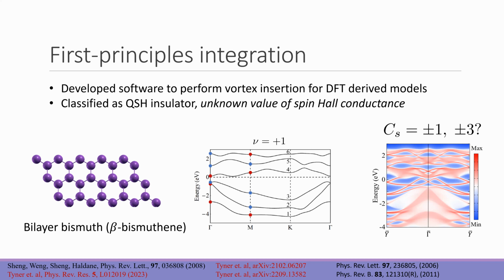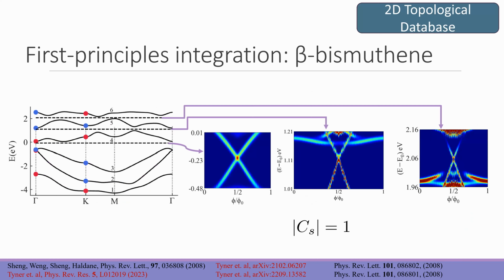They tried to distill this by looking at edge states, but the edge states are kind of complicated here. It's hard to just draw a line through the mid gap, through the bulk gap there, and determine what your spin Chern number is based off of how many times you cut these bands on the surface. So we did a first principles calculation and then wrote this software to do this insertion in our more realistic band structure here. And we looked at the 3 band gaps that you can access there as a function of filling, and looked at this local density of states on the flux tube.